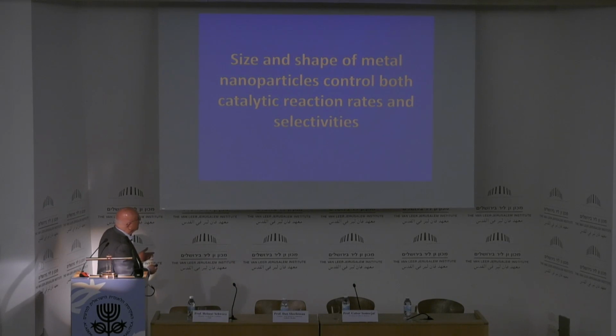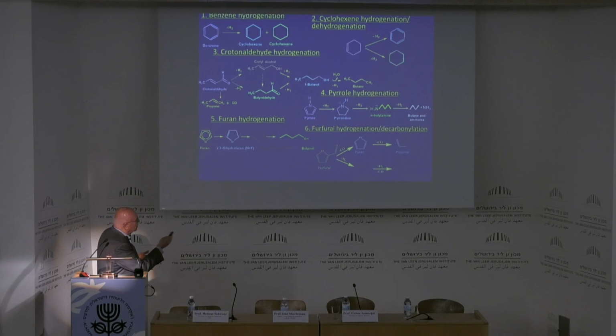Now, the finding, which is very important, is that the size and shape of the nanoparticles control the catalytic reaction rates and the selectivities. Now, we have studied many reactions. These are rather simple reactions, but they are very easy to identify what it does. For example, here the furan is hydrogenated to dihydrofuran and then to a linear molecule. So all these molecules undergo changes that we can follow as a function of size of the nanoparticles.